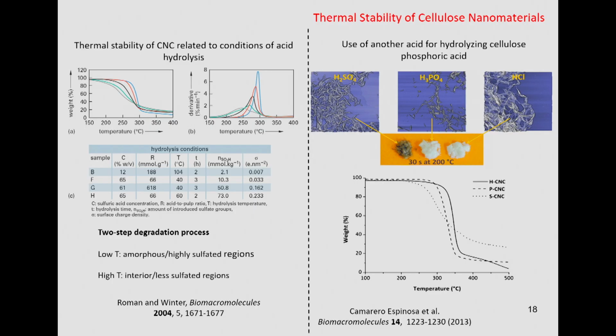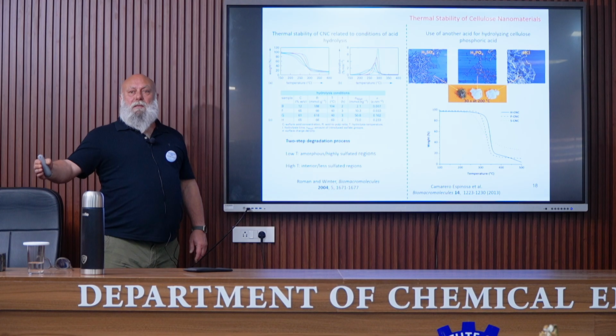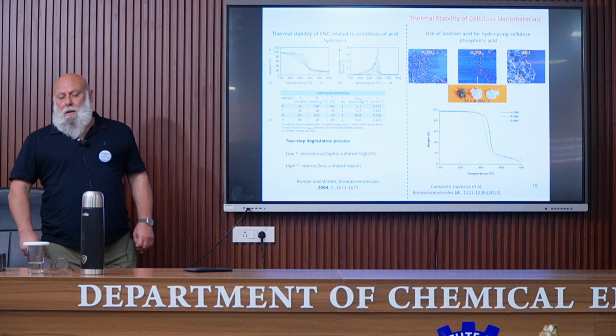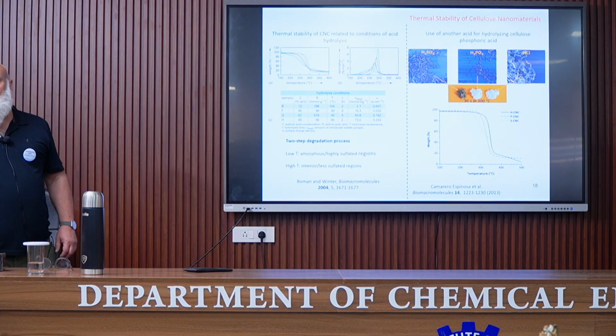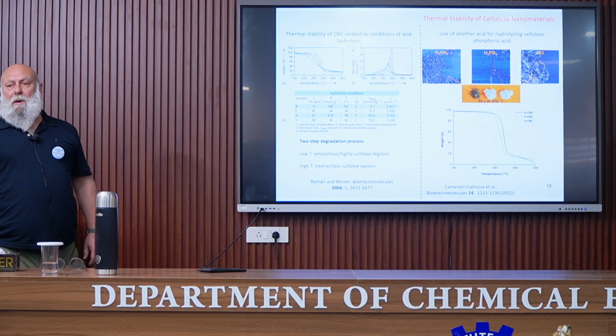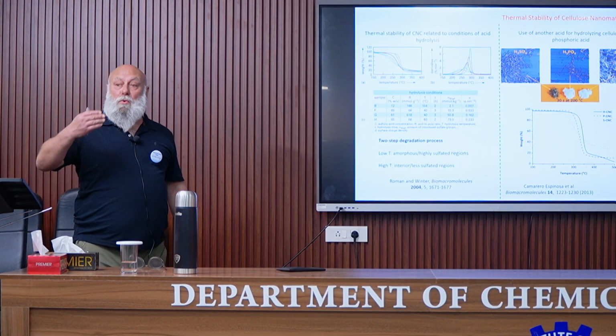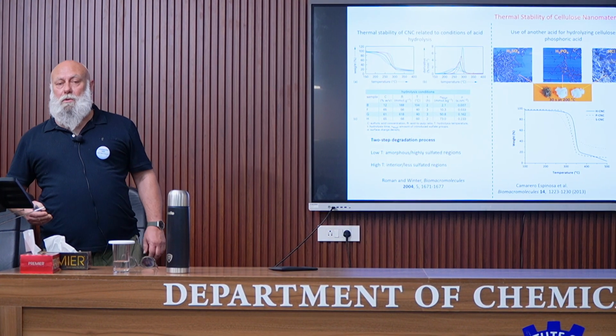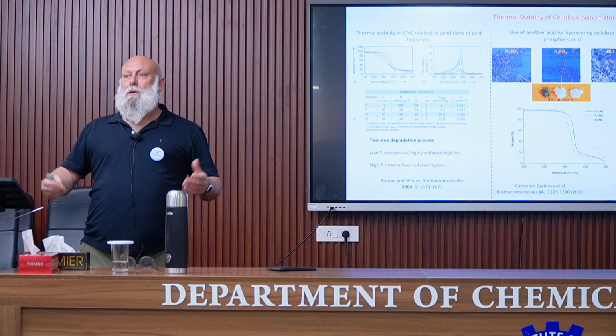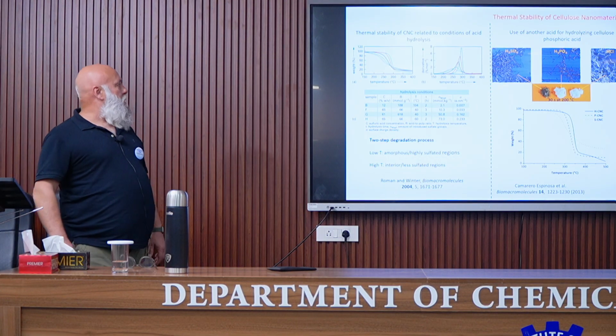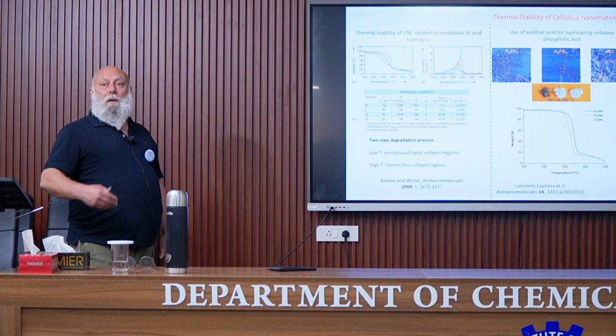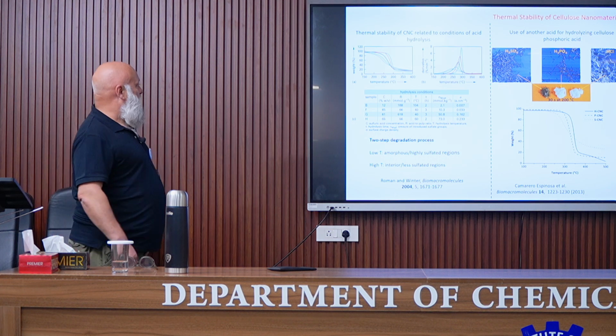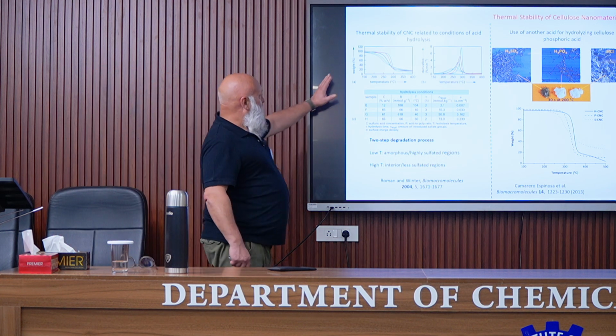Now regarding the thermal stability of cellulose nanomaterials, it was shown that the thermal stability of cellulose nanocrystals decreases when the acid hydrolysis treatment is performed with sulfuric acid. And remember that usually sulfuric acid is used because a good, stable suspension results from this process because of the grafting of sulfate groups. But in this study,